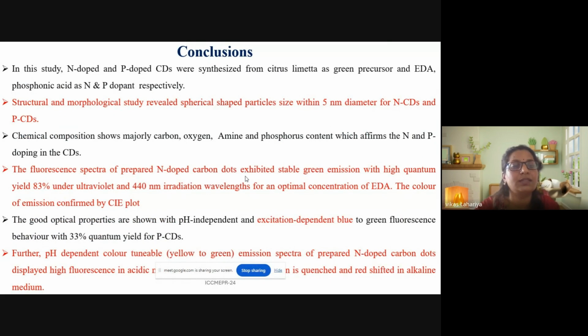So, conclusion: in this study, N-doped and P-doped carbon dots were synthesized from Citrus limetta, sweet lime juice, as a green precursor, and EDA and phosphoric acid were used as the N-dopant and P-dopant respectively. The structural and morphological study revealed a spherical shape, with particle size within 5 nanometers for the N-doped and 3 to 5 nanometers for the P-doped.